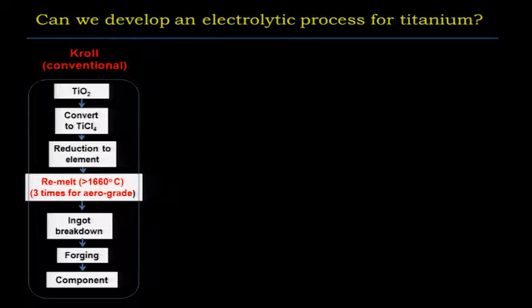And in the conventional titanium method, you take titanium dioxide, which is almost as abundant as aluminum oxide, and iron oxides, and you convert it to titanium tetrachloride, you reduce it, and then you remelt it three times. And this is remelt three times at 1660 degrees C. Hugely energy intensive. You do need this three times for aircraft quality titanium. So the real question is, can you actually get an electrolytic breakdown and refinement just in one fell swoop like